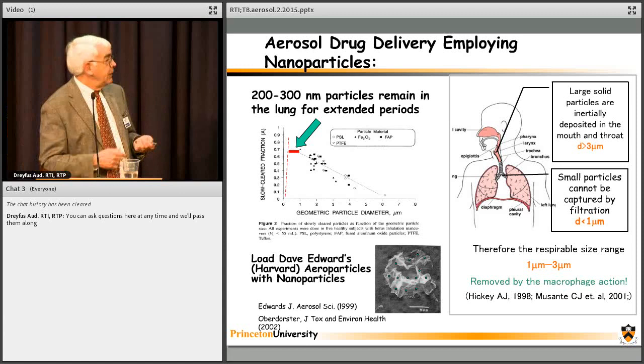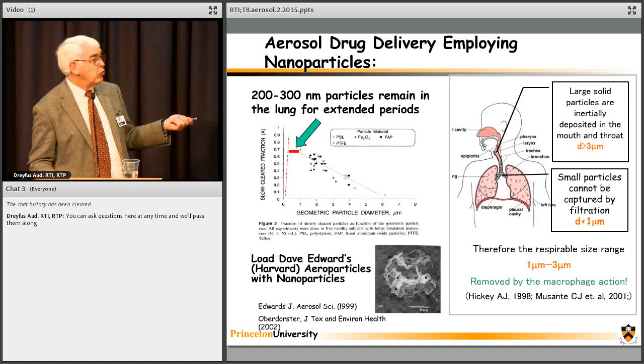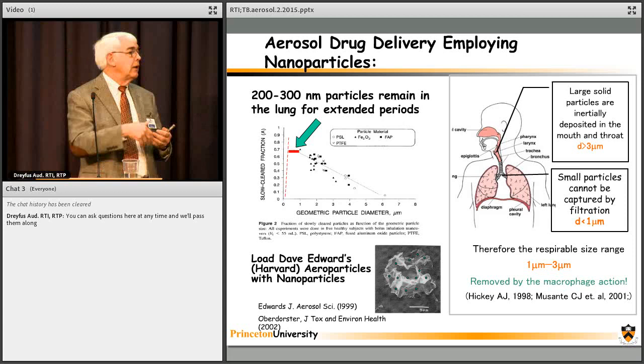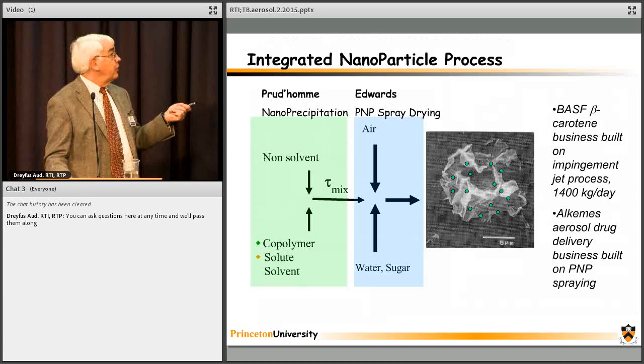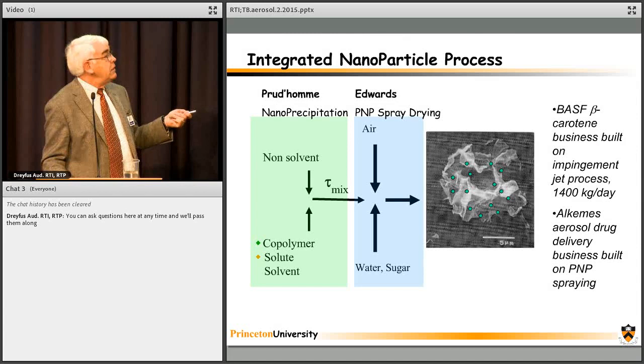And Dave Edwards is the expert at coming up with spray drying conditions that will give you this crenellated surface. You want that because you don't want these particles sticking together inside the inhaler, so it allows them to be aerosolized much more efficiently. So what we're going to do is, as I said, we're going to take our formulation, and we can take our mixer right into the inlet of a spray dryer where this sugar or leucine is coming in one stream, and make the nanoparticles in situ.